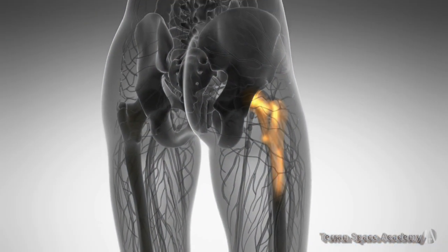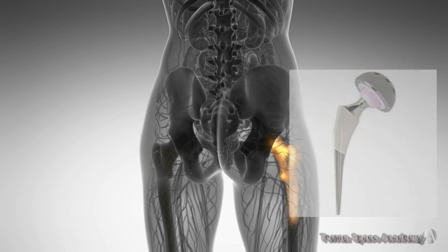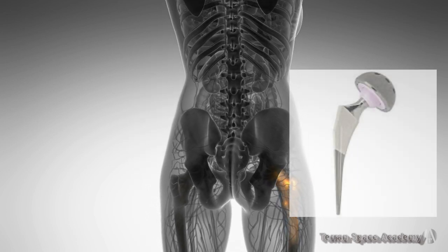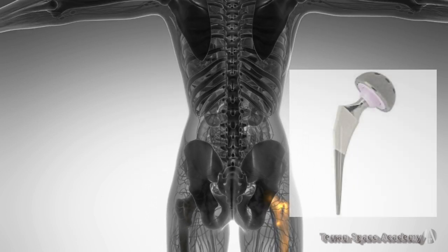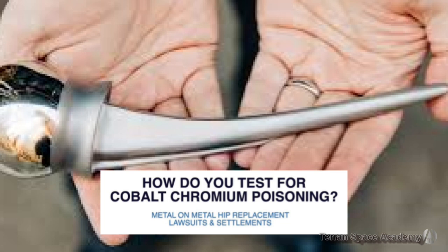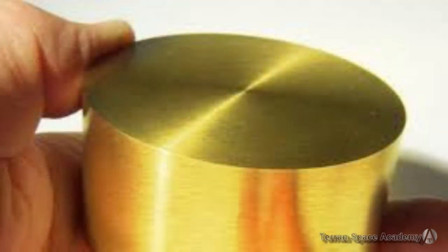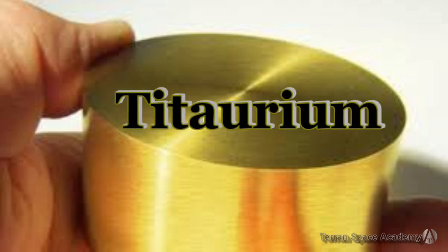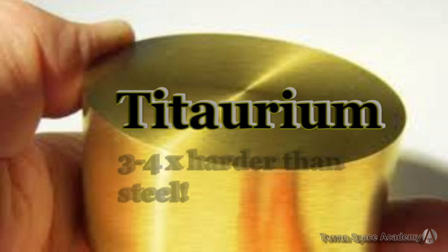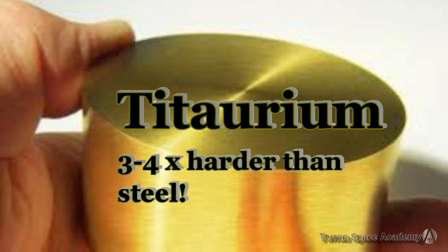Scientists at Rice University were searching for a good metal for artificial hips and other joints. Cobalt chromium had been used, but the cobalt would dissolve into the surrounding tissues and cause heavy metal poisoning, and the joint would have to be removed. Titanium has been used since it is exceptionally light and strong. The scientists discovered, however, that an alloy of titanium and gold, which I will call Titaurium because it sounds so cool, was 3 to 4 times harder than the best steels.